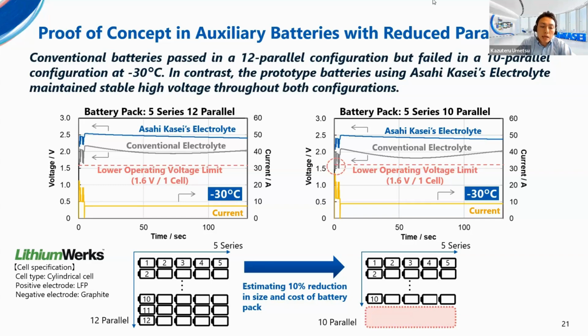The blue and the gray lines are the corresponding voltage curves of the acetonitrile and the standard carbonate electrolyte. The lowest operating voltage was 1.6 volt per cell, and both electrolytes passed this condition. Next, please look at the right graph.